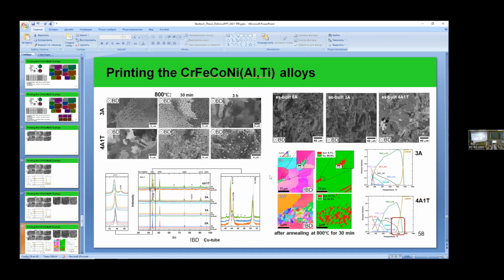The phase we observed was between the small grains, but it is based only on SEM observation. It's not TEM observation where we obtained TEM diffraction and strictly recognized it as the sigma phase. But we suggest that we observe the sigma phase and that it forms between the grains, and after further heat treatment there are larger grains or precipitates of the sigma phase.